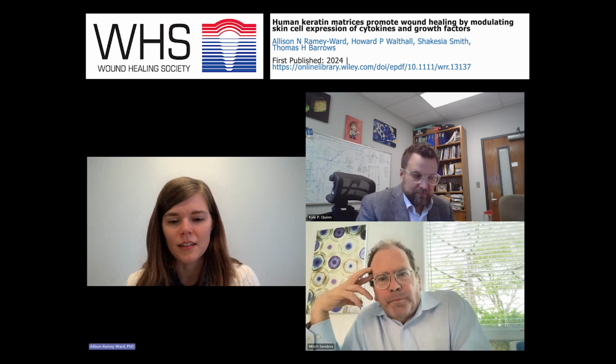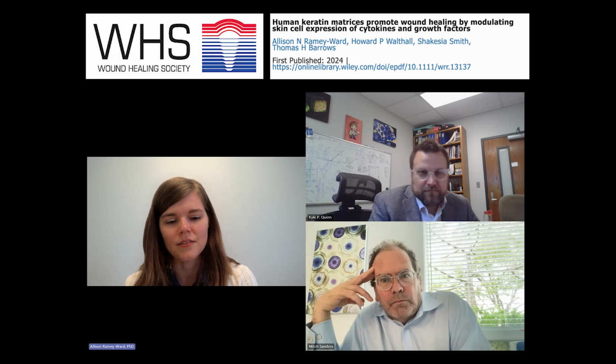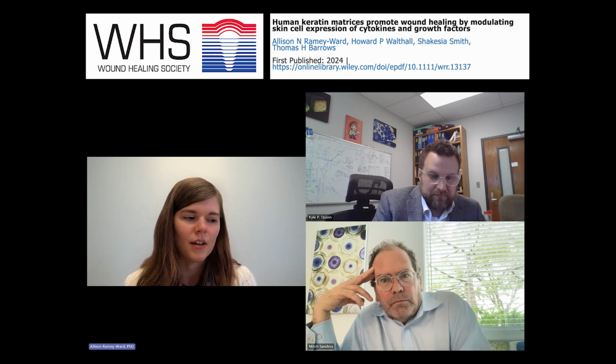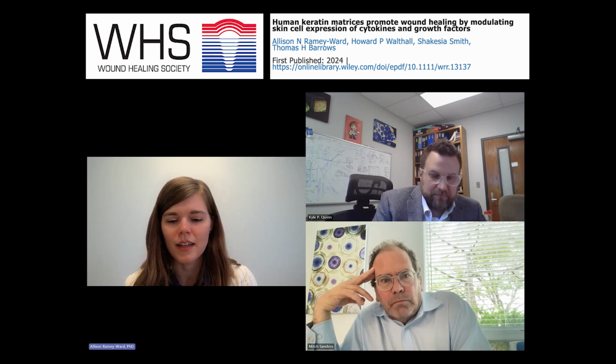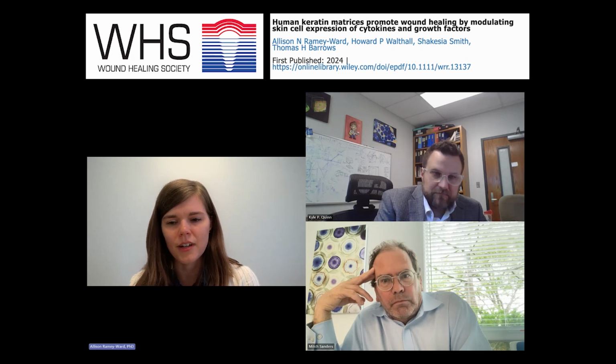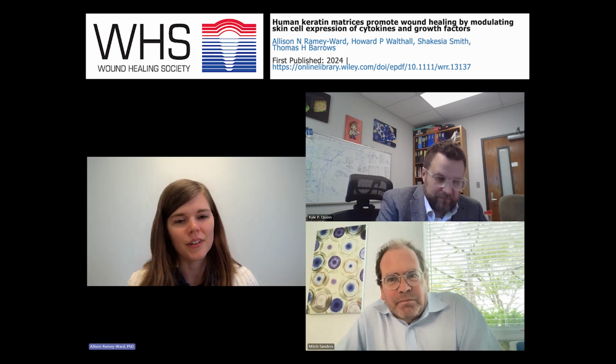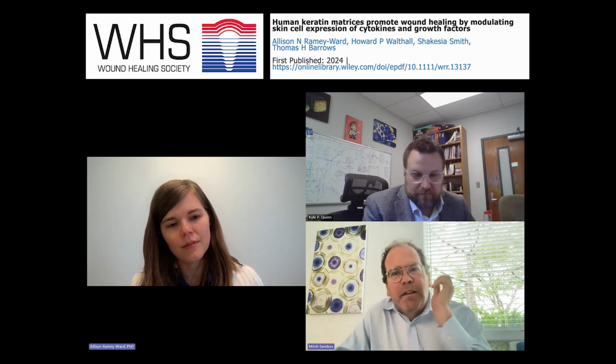We noticed that the product, this human keratin matrix, is pretty robust. It's fairly stiff. It's almost 1 megapascal as its ultimate tensile strength. That was pretty interesting, especially for a hydrogel. Those are typically much softer. And we see that it's fairly resistant to hydrolysis as well. Again, that was something we weren't necessarily expecting, but was very interesting. We looked out to 7 days for that.